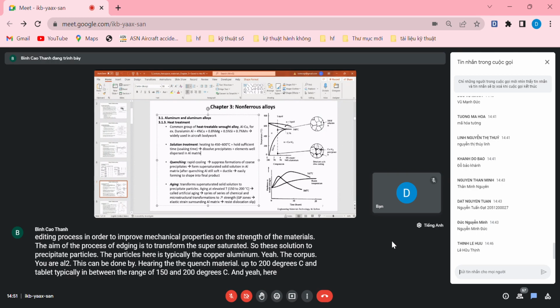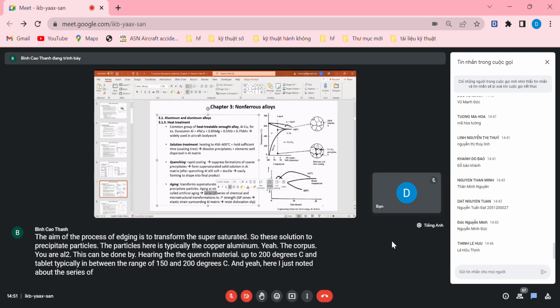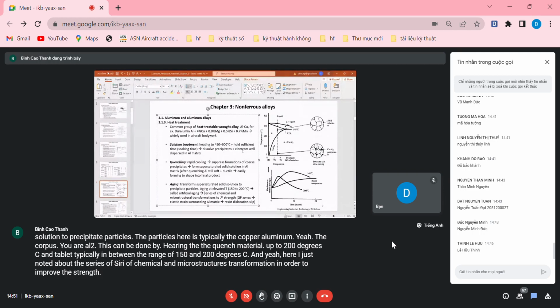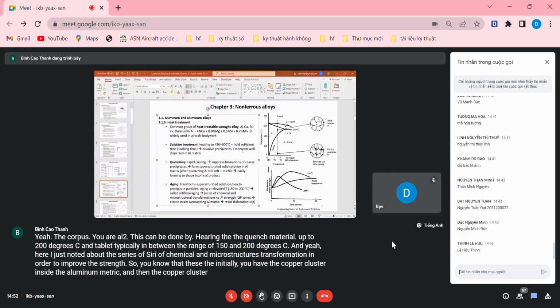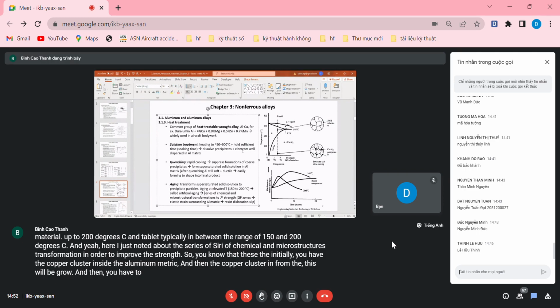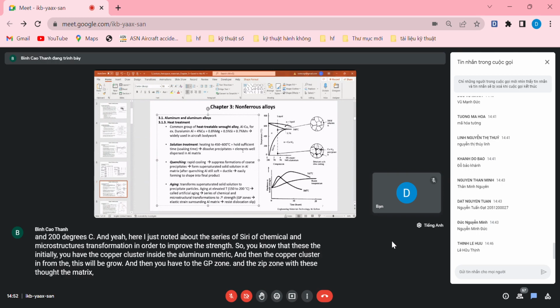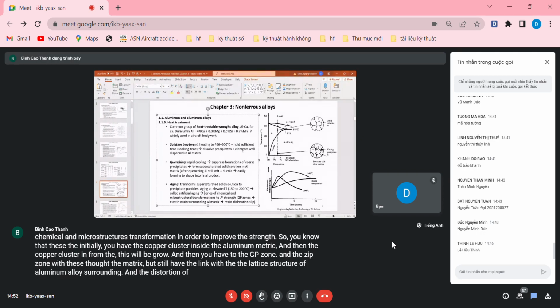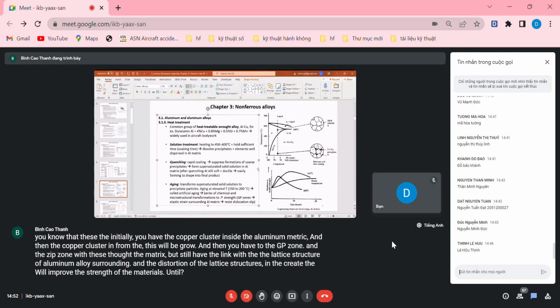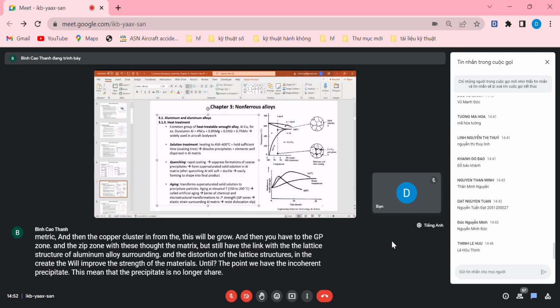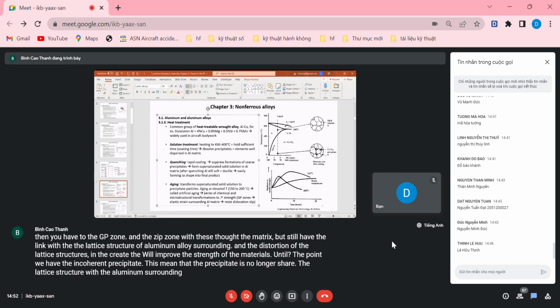Here I just noted a series of chemical and microstructure transformations in order to improve the strength. Initially you have copper clusters inside the aluminum matrix, and then the copper clusters grow into discs, and then you have the GP zone. The GP zone will distort the matrix, but still has a link with the lattice structure of the surrounding aluminum alloy, and the distortion of the lattice structure will improve the strength of the material, until the point where we have the incoherent precipitate. This means that the precipitate no longer shares the lattice structure with the surrounding aluminum. In that case, we have a reduction of the strength.